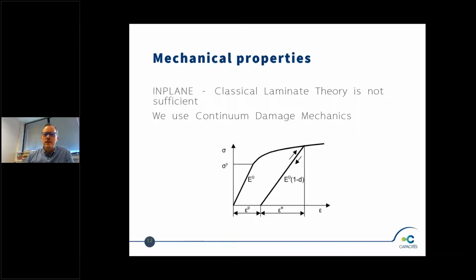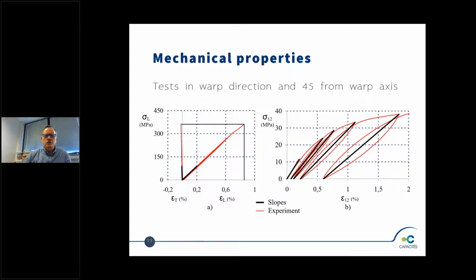So in the plane, the classical laminate theory is not sufficient because the DNA of the model that we applied in the next slides is based on continuum damage mechanics. So basically on the curve that you have on the screen, strain is on the x-axis and stress on the y-axis. When you increase the stress, at first you have E0, which is the classical linear elastic response of the material. And by increasing the stress, you will provoke some micro cracking in the material. And if you remove the load, you will not come back to the origin of the strains. So this kind of behavior has to be taken into account in order to represent well the behavior and the stress distribution inside the material. So we have the ability to model the material.